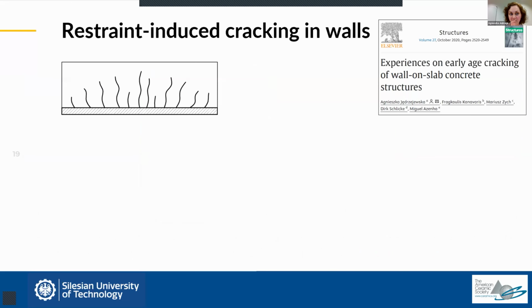In such elements, we observe the following cracking pattern. So this simple scheme shows you how cracks usually look in such elements. We see that the cracks are vertical in the midspan of the element, and then they decrease in height and become a little bit slanted towards the ends of the element. I don't want to dive deeper into this topic. If you are interested in a more detailed characterization of cracking that we see in the walls, I refer you to another of the works of our team. But I would like to explain what is the reason for such cracking in the walls.